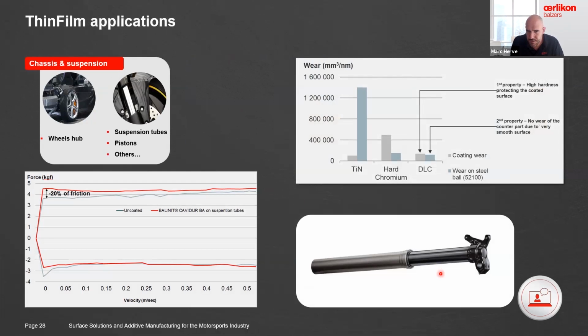Here, a very common application that a lot of people see now on the market is the coating on the suspension tube, for example. Very often you see this gold color on the tube, which is in this case what we call a titanium nitride. I think it could look nice on the bike, but I'm more about technical properties than really the look. So this is why I prefer to apply a DLC coating on the tube, because we combine again the hardness for the wear resistance, and then a very low friction. We did some tests with a couple of customers, and we measured up to 20% reduction in terms of friction. And this translates to a benefit for the driver because the suspension will be a little bit smoother and you get a better feeling with the track. So here is a good example where friction is really making a difference.